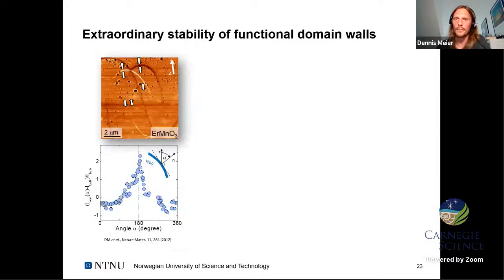And that's one of the key ingredients we have to have if we play with the domain walls as electronic components. A secondary effect, because I have head-to-head and tail-to-tail walls, that's what you see here. We measured that back in 2012: at the head-to-head walls, where we have positive charges, we see reduced current. Here it's darker than in the bulk. At the tail-to-tail walls, you see bright lines, which means that conductance is enhanced with respect to the bulk. And in between, it gradually changes from insulating to bulk-like at the neutral walls, where there are no bound charges. So these conductance maps, which are collected with a biased tip scanning across the surface and then recording the current, really show you the differences at the domain walls, and that it's driven by the polarization charges. And the wall conductance changes gradually with the orientation of the wall as control parameter.